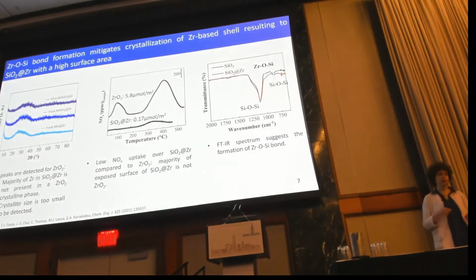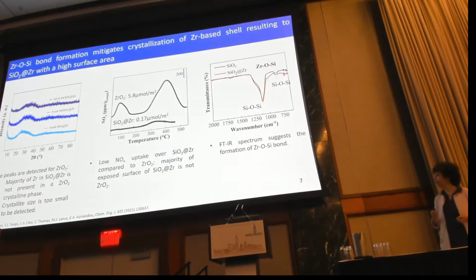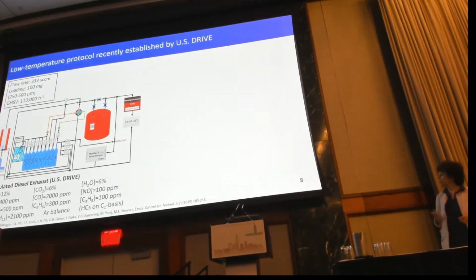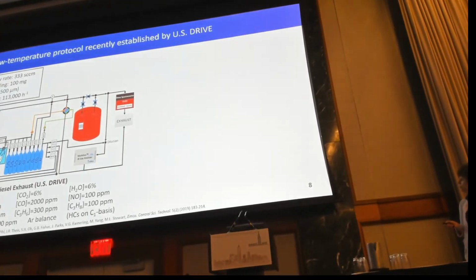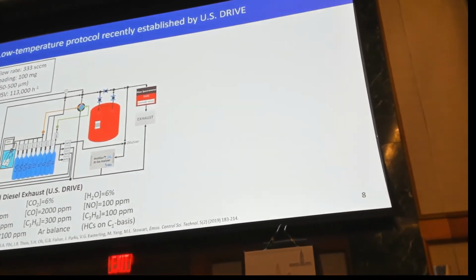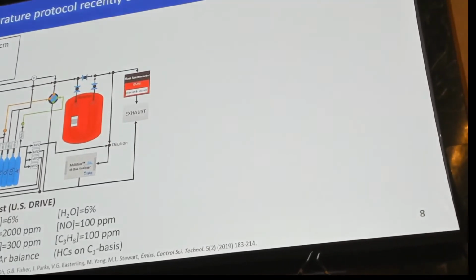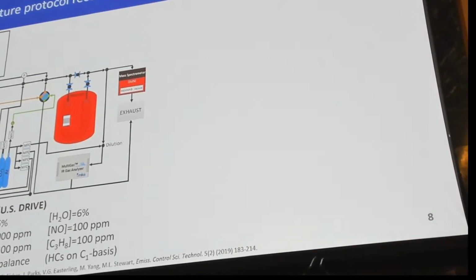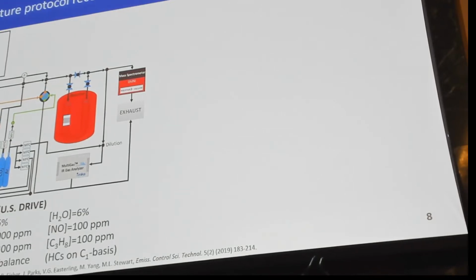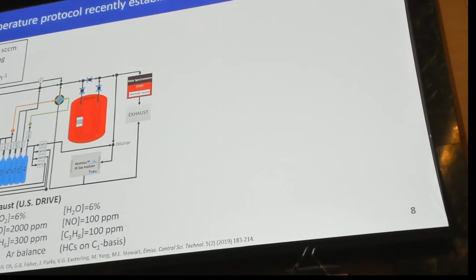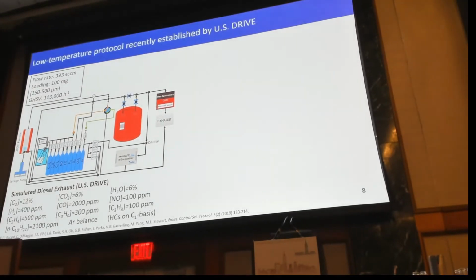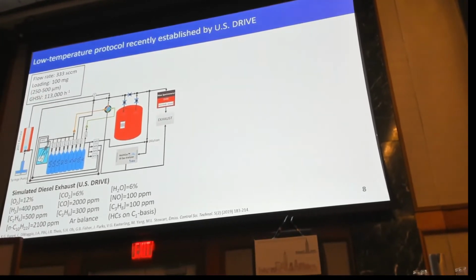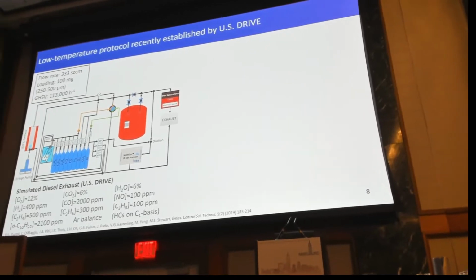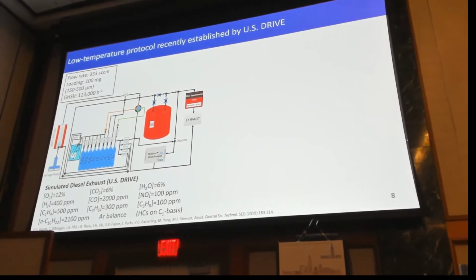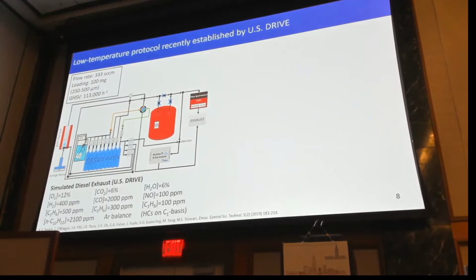So we're very excited about this material and we wanted to evaluate its performance. So here you can see this is a home-built microreactor in our lab. We deposit 100 milligrams of catalyst in the quartz tube, and the flow rate that we're using is 333 SCCM. The catalyst is pressed and sieved to 250 to 500 microns, and this is our gas hourly space velocity. So we want to simulate the diesel exhaust, and for this reason we flow all these molecules that you see down there.